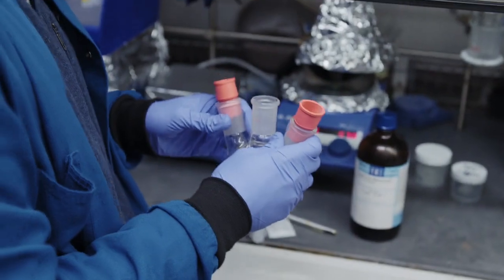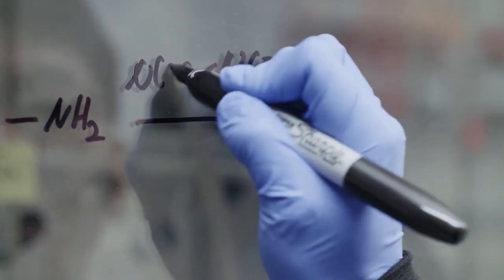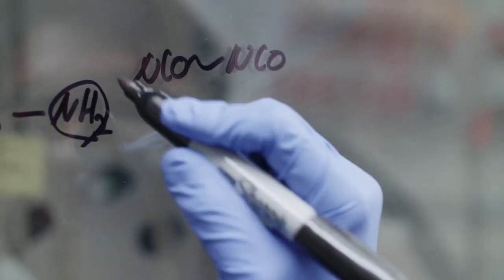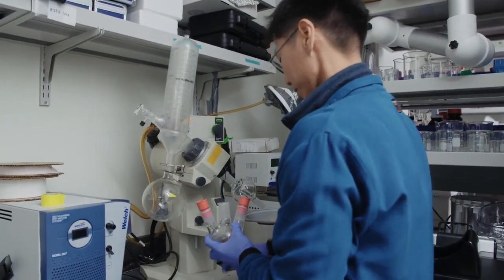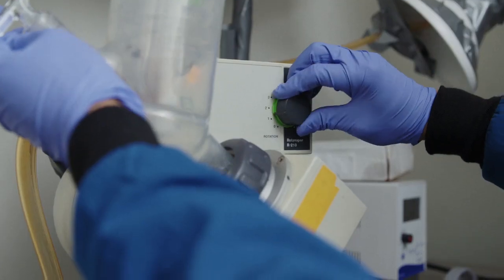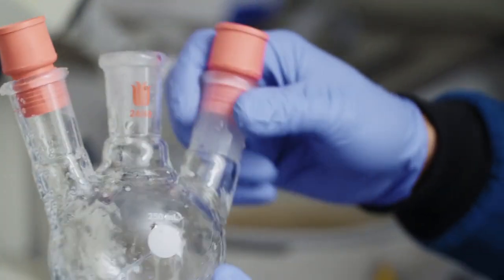The self-healing properties came from the incorporation of dynamic bonds, for example hydrogen bonding. In many biological systems, hydrogen bonding exists. We incorporate hydrogen bonding sites that can break if we stretch the material, use force. But this breakage is highly controlled, so the material will not form crack and can continue to elongate.